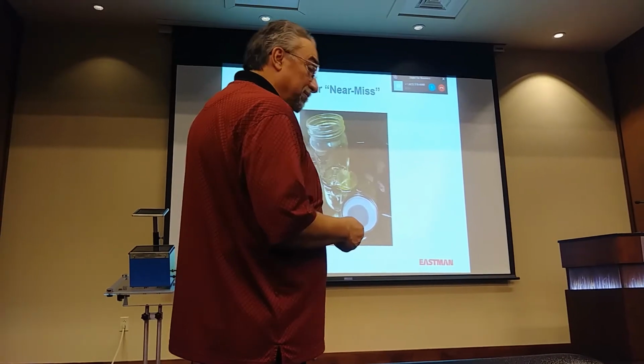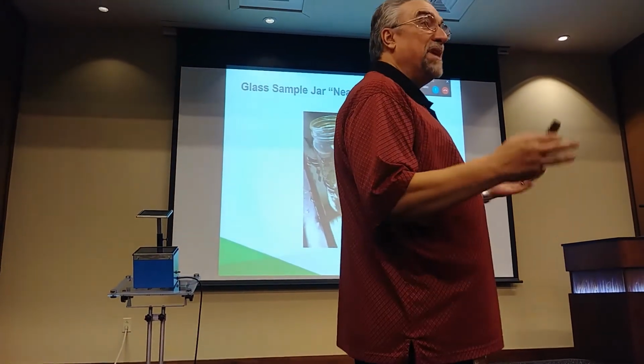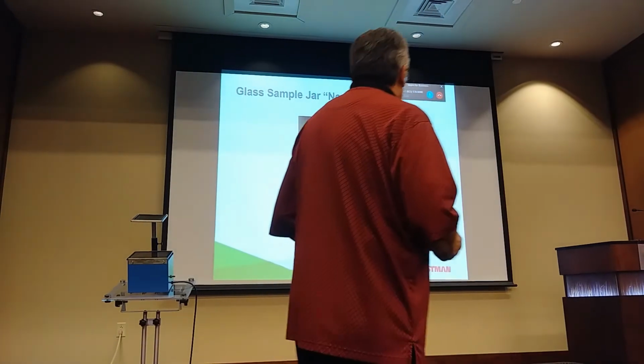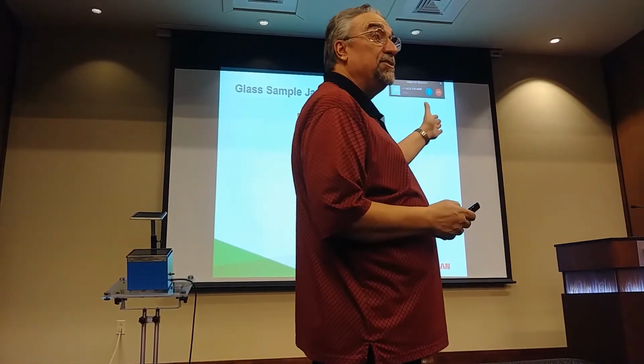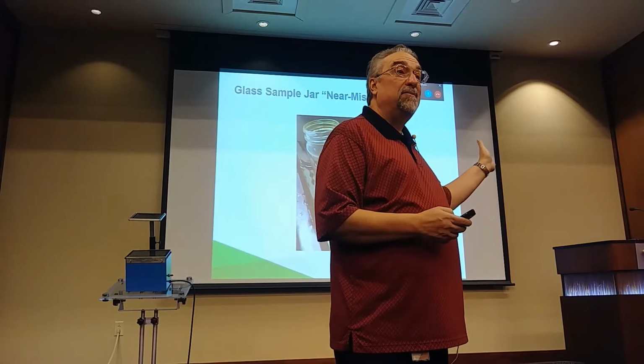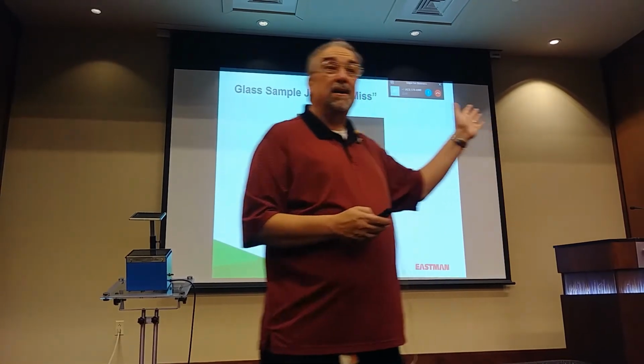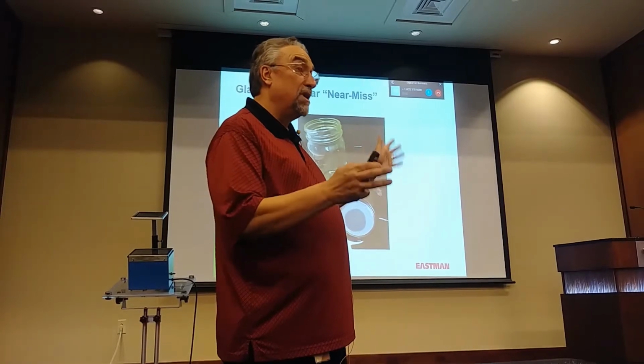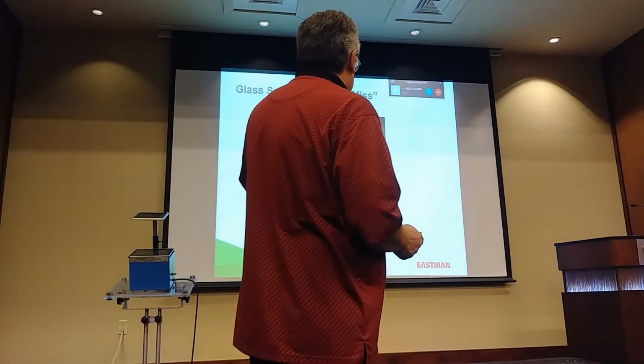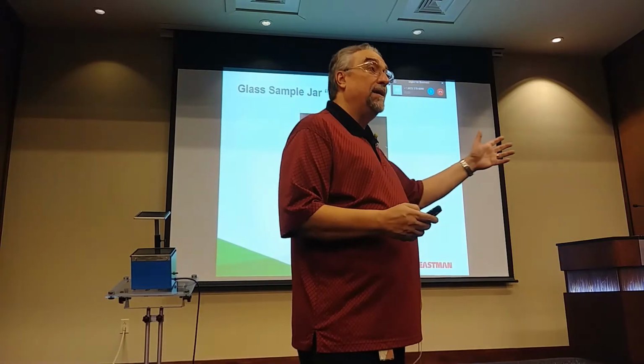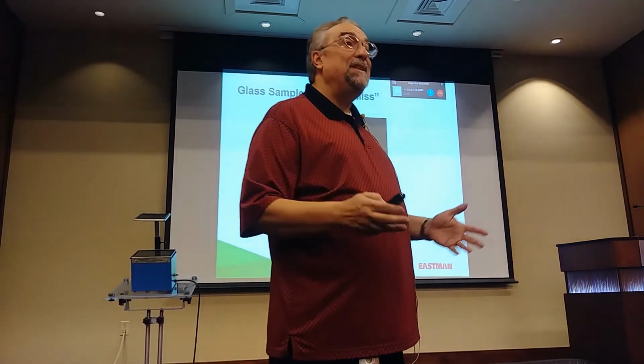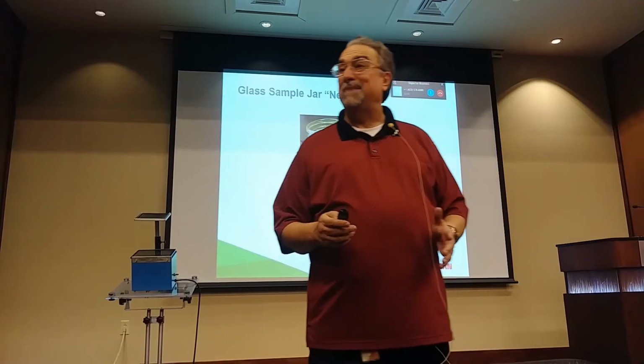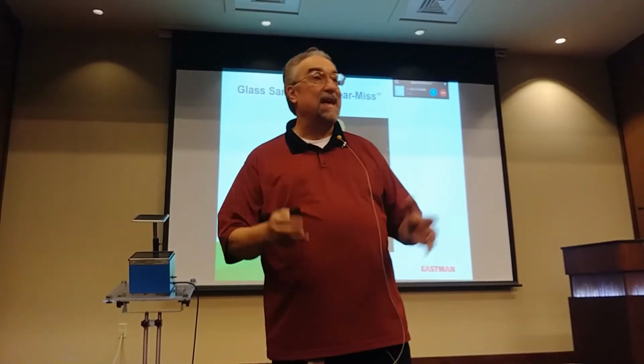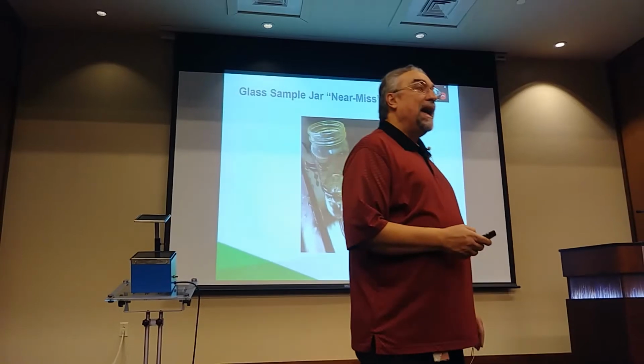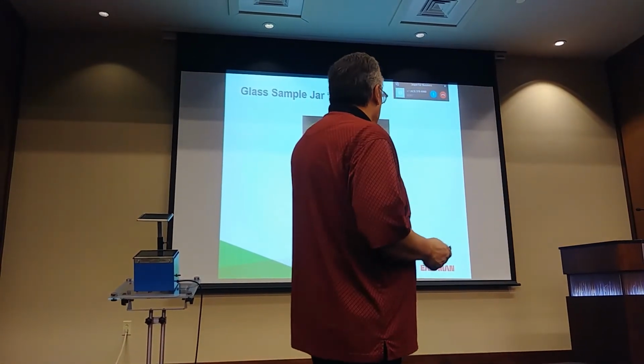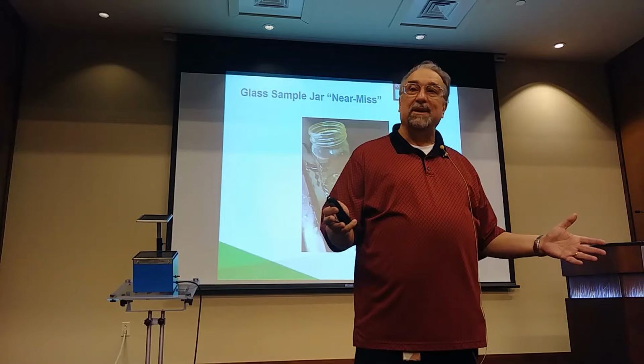I did this, and this is a near miss that I turned in at work because I thought these were heat treated jars, but they're not. They're just simply lead glass jars that we use arbitrarily, and I poured some hot resin into it. Now, I had done it many times. I had poured hot resin into jars just like that over and over again. And this was the first time that I had ever had one where the bottom just dropped out of it.